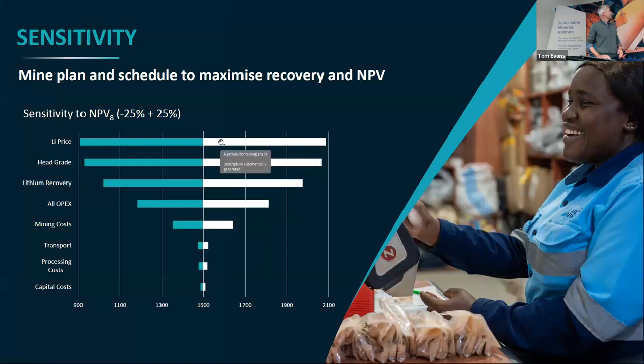And this is quite interesting when you look at the sensitivity in the study. So this is sensitivity to NPV. So our current NPV sits at that 1.5 billion. And then this is plus or minus 25% on the various levers. So you can see that the biggest lever that impacts NPV is the lithium price used in our study. Spodumene concentrates currently selling at around $3,500 per ton. That's SC6. It's been as high as over $6,500 per ton last year. But you can see that if you increase that spodumene price by plus or minus 25%, it does have a big impact on the NPV. It's still very healthy NPV at the 25% below the $1,500 per ton we used roughly in our study.